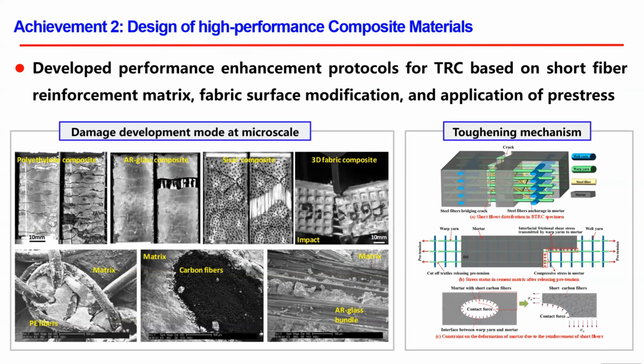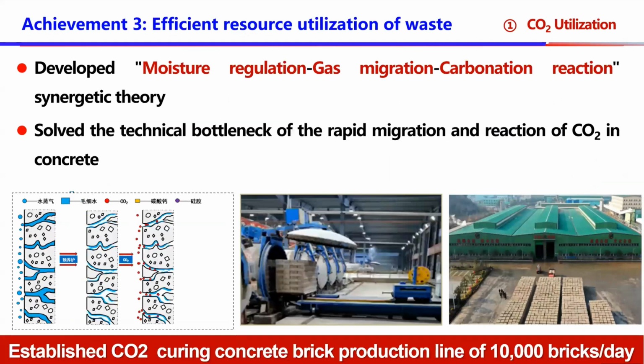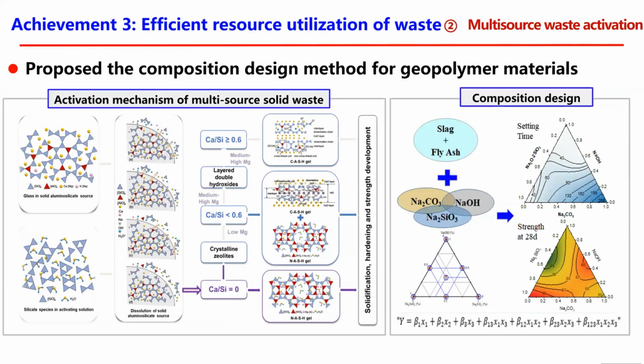And we also work on designing high performance composite material, and actually Professor G is mainly working on TRC based reinforced cementitious material. Our third area is efficient use of waste material, including carbon mineralization. I will talk in more detail later, and also the activation of solid waste material. Actually, in our laboratory we found the relationship between the calcium to silica ratio and the formation of either C-S-H or C-A-S-H. And we also use chemical activators like sodium carbonate, sodium hydroxide, and sodium silicate to regulate the setting and property development of alkali activated material. So that's the kind of topics we have been working on.